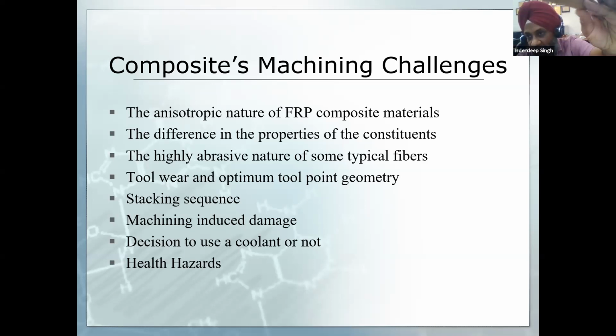So it is a lightweight composite material. You can appreciate the fibers running in both directions, and in the Z direction through the thickness, there are different layers of the composite. So you have different layers and fibers in both the X and Y plane. Therefore, making holes in these materials becomes a challenge because of the anisotropy. Second, the properties are different.